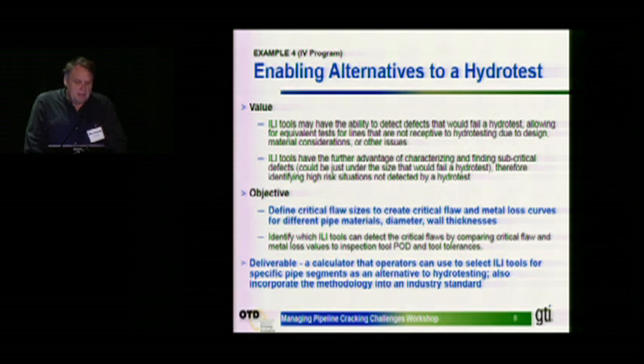Another project which we have is enabling alternatives to a hydro test. We've heard a lot of talk about that today. So here the objective is to define the critical flaw sizes and to create critical flaw and metal loss curves for different pipe materials, diameter and wall thicknesses, to identify which ILI tools can detect the critical flaws by comparing critical flaws and metal loss values to inspection tool POD and tool tolerances. And once again, the deliverable will be a calculator that operators can use to select the ILI tools for specific pipe segments as an alternative to hydro testing, also incorporating the methodology into an industry standard.